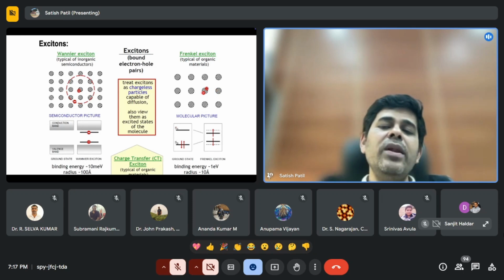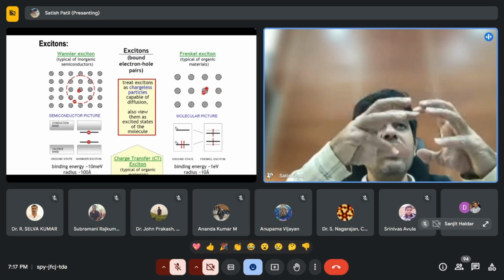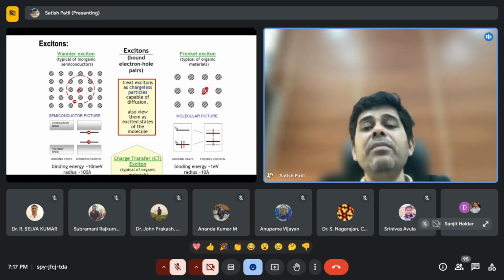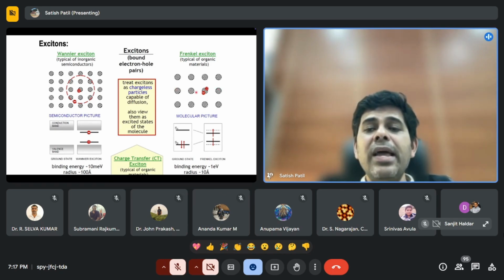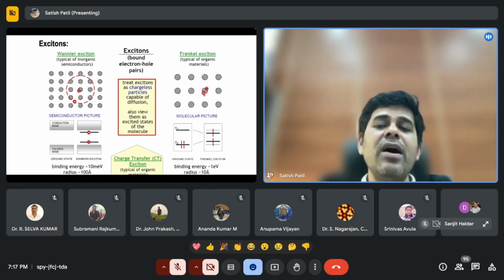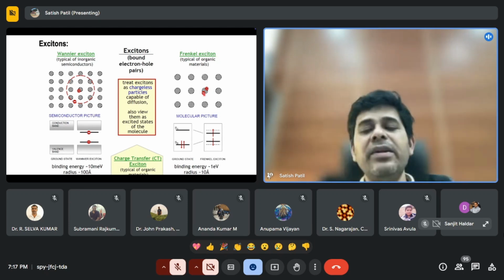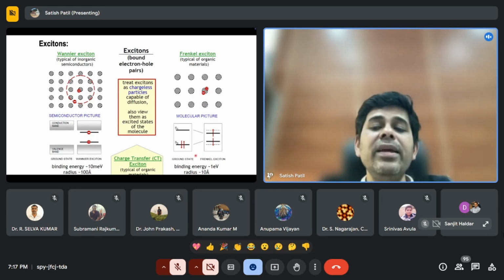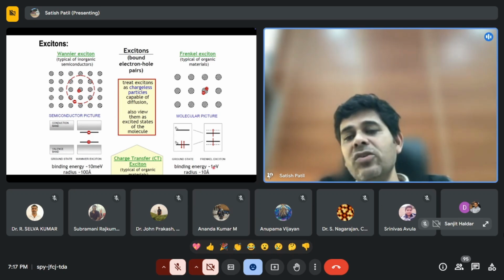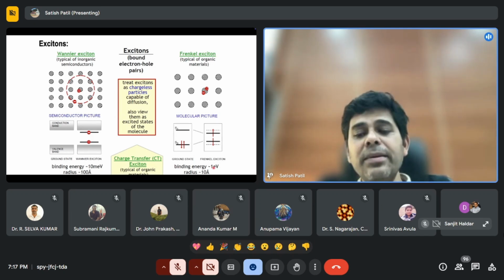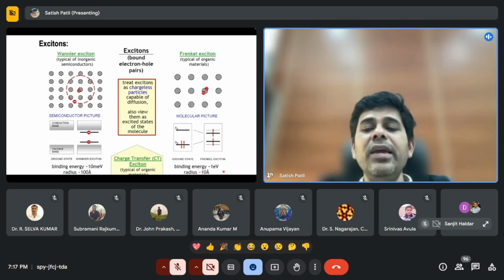You see this hole and electrons are localized on some particular one-dimensional chain here. And then they recombine very fast rather than separating out. The experimentally observed binding energy of this one is in the range of 0.5 electron volt to 1 electron volt. And as I mentioned, the room temperature energy is 27 millielectron volt.